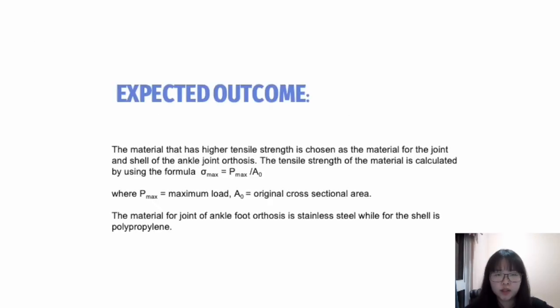The expected outcome for this experiment is that the material that has higher tensile strength is chosen as the material for the joint and the shell of the ankle-foot orthosis. The tensile strength of the material is calculated by using the formula: maximum tensile stress equals maximum load over the original cross-sectional area. The material for the joint of the ankle-foot orthosis is stainless steel, while for the shell it is polypropylene. So that's all from me, and I will pass to Alya to explain lab 2.